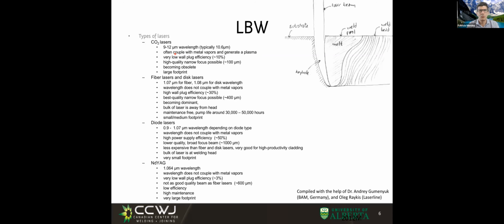The visible range reaches to about 800 nanometers, right? 0.8 microns. Now, a CO2 laser is 10 times longer wavelength. It's 9 to 12 microns wavelength. Let's call it more or less 10. And we're gonna see this number that kind of makes sense. So it's a very, very, very long wavelength. And that has a couple of challenges. One is that metals are very reflective at that wavelength.